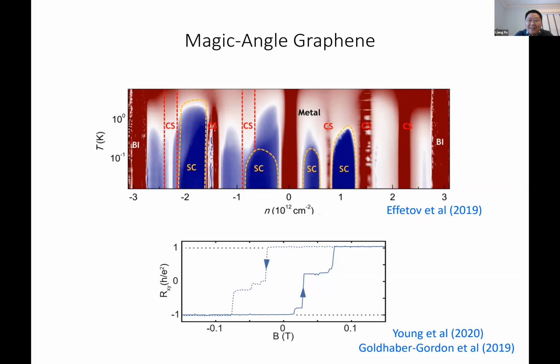A year later, this is work from Efetov's group in Spain, again on magic angle graphene. But now we see that the phase diagram has certain similarities, but also differences. We see that insulating states appear at all integer fillings, and they are separated by the superconducting domes. So if you look at this, perhaps it's not that close to the phase diagram of the cuprates.